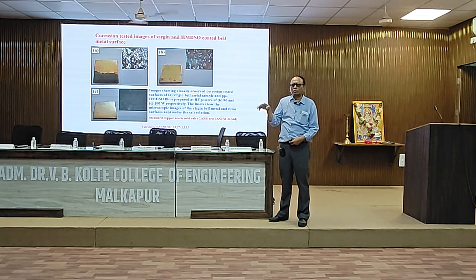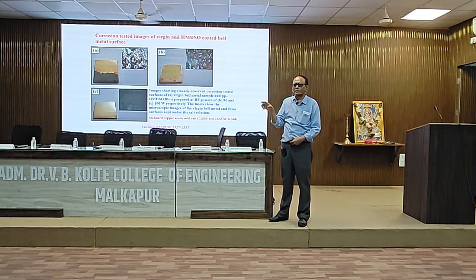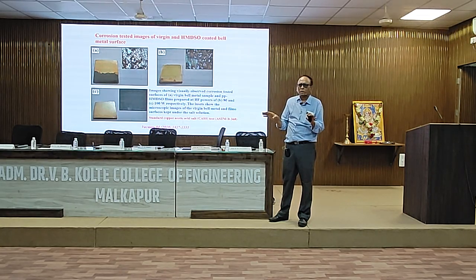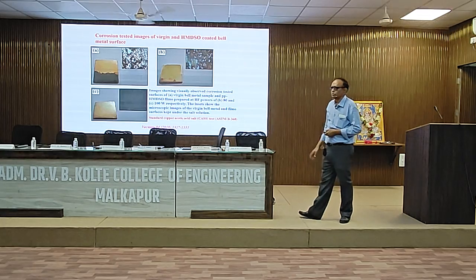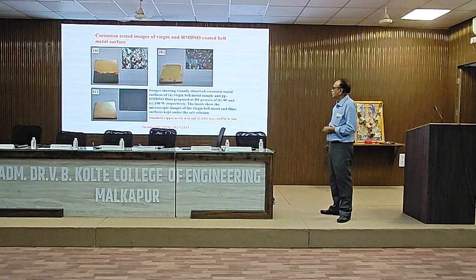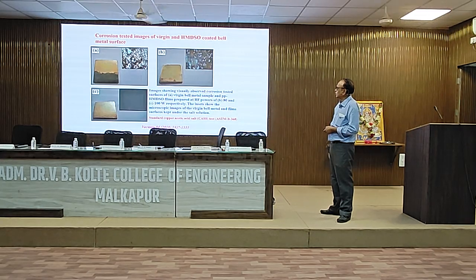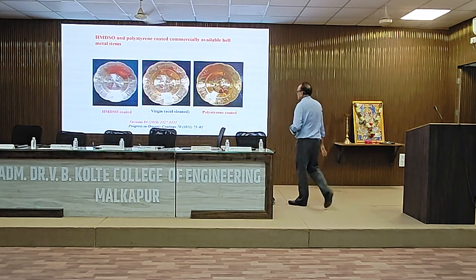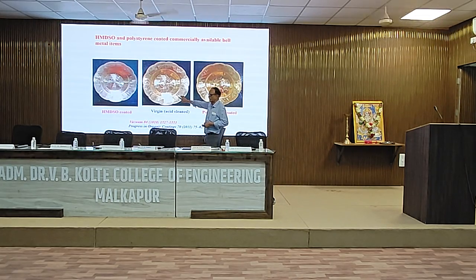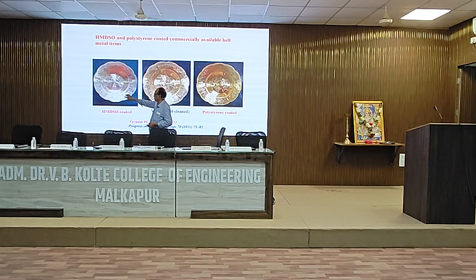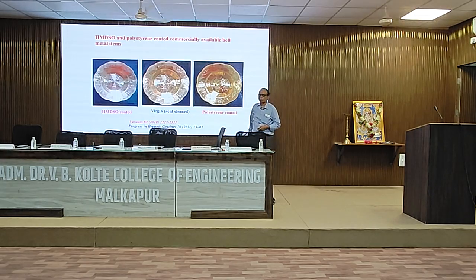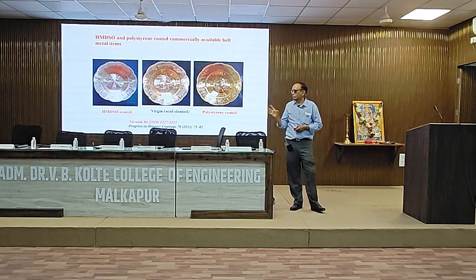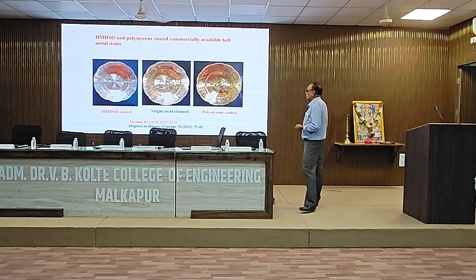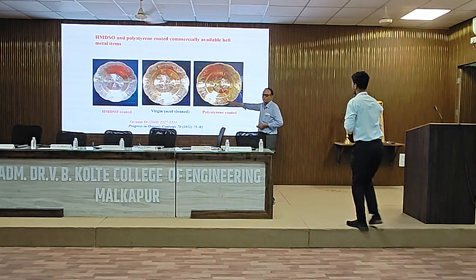But earlier, lacquering, like putting turpentine and all these things, was allowed. Nowadays, it is environmentally banned, and if you put a turpentine coating, you cannot export it. So there was a necessity to develop a coating on these components using this plasma process. We have done that. These are the acid cleaned components, and this is how it looks. This is a hexamethyl disiloxane plasma coated component, and this is one which is again by plasma process polystyrene coated. Polystyrene was decomposed in the plasma medium, and once it was deposited, the corrosion tests and all those things were done.